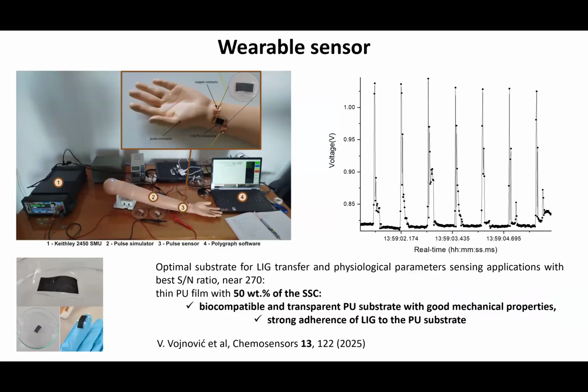Because it's mechanically so favorable, this polyurethane is stretchable, as I said, and flexible. We've tested it as a wearable sensor for heartbeat. Now we no longer use the arms of human subjects. We actually have an artificial arm that has a real pulse. A part of the arm pulses, and you can set the intensity and the repetition rate of these pulses, which is excellent for gauging the sensors based on these materials against one another.